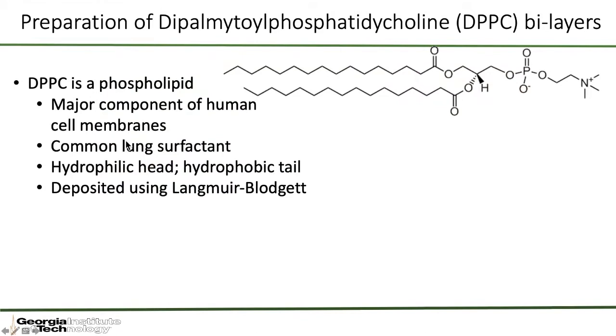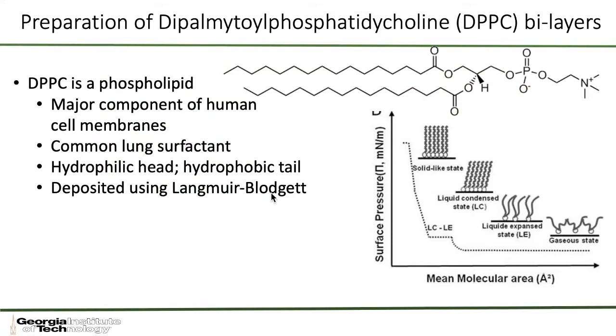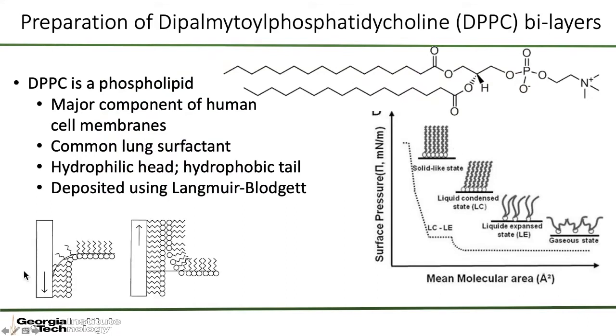These molecules, as a phospholipid, have a hydrophilic head and a hydrophobic tail. And we can deposit them onto our surfaces using Langmuir-Blodgett deposition. Basically, Langmuir-Blodgett deposition is a technique where we take these molecules and deposit them onto a water trough, or a bath of water, and since they have a hydrophilic head, they self-orient, right? The head is attracted towards the water, the tail away. Then by slowly closing a barrier, we can compress those molecules on the surface. As those molecules are being compressed, they self-order. And then by drawing a substrate through that film, we can deposit those molecules onto the surfaces, ending up with our nice little bilayer films.